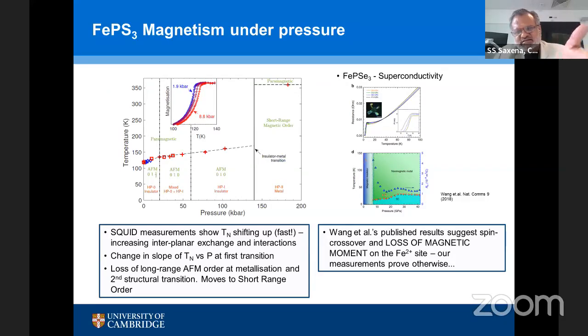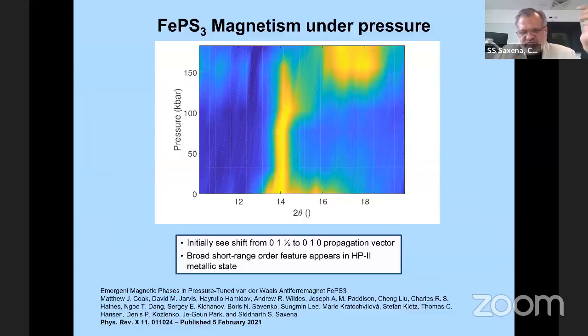That the system goes from being, in this case an antiferromagnet because we're looking at the full FePS3, and this is a measurement using neutrons. So we can directly not see any long range order at all, but we can derive, using reverse Monte Carlo from this data, this is what you get. If you have a look at this PRX paper, you will see how we treated the data. There's no long range order, but there is magnetism in the system. So there's no moment on the iron site.